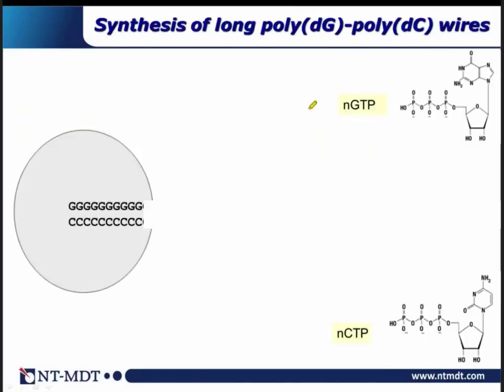No, this is not the way we are making our wires. Again, we use polymerase, but the mechanism is different. We discovered 7 years ago that polymerase, in addition to the catalysis I have been showing you, can do another kind of job. We take what I would term a template-primer system, which consists of, let's say, 10, 12, 13, a small number of Gs in a row. This is a double-stranded structure, which is extremely small, only 10 or 12 bases maybe: only Gs in one strand and Cs on the other strand.